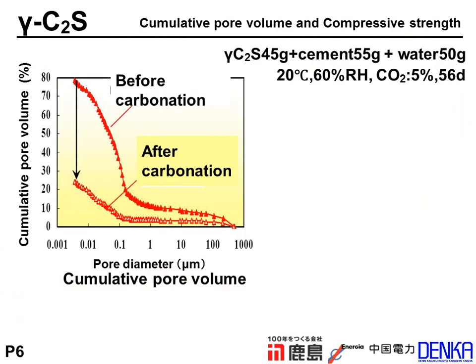So this figure is the cumulative pore volume of the paste consisting of gamma C2S, cement, and water. The curing condition is 20 degrees Celsius and 60% relative humidity, and the concentration of carbon dioxide is 5%. The curing period is 56 days. You can see that the cumulative pore volume before carbonation is around 75%, but after carbonation the value is around 25%, so it decreased by carbonation.